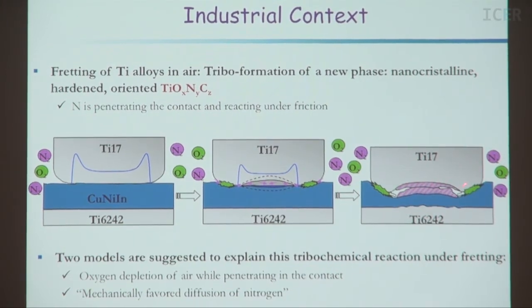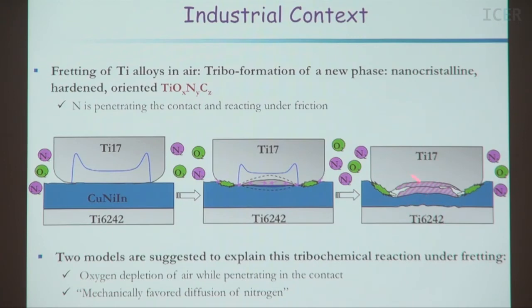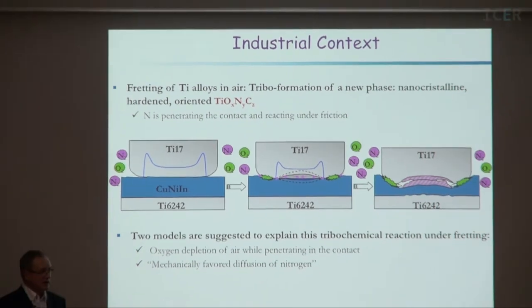So we want to explain why there is a lot of wear in this area. From the analysis, it was detected that this pink material is made of a titanium oxynitride carbide layer. This is a very hard material, much harder than titanium alloys, and this is where the hard particles make the wear of the two pieces. So the question is why nitrogen can react with titanium, because normally titanium reacts with oxygen.